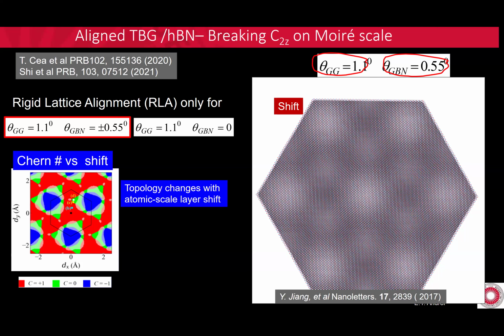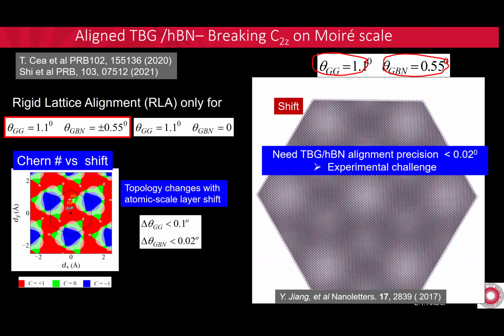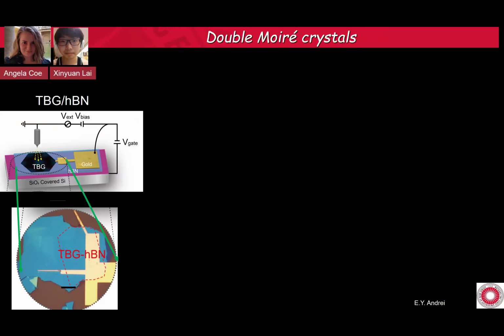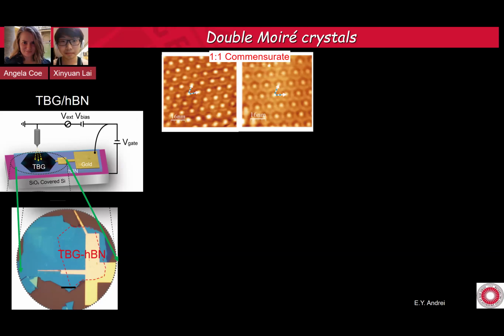You see what's going on with this topic. Unless the precision of alignment is 0.02, which is absolutely impossible. We don't know how to align 2 different materials; the technique doesn't work. So it is a big experimental challenge. That brought us to our STM. Here is a picture of the sample: twisted bilayer graphene on boron nitride. These are our electrodes. And then we look at the pattern that we form.